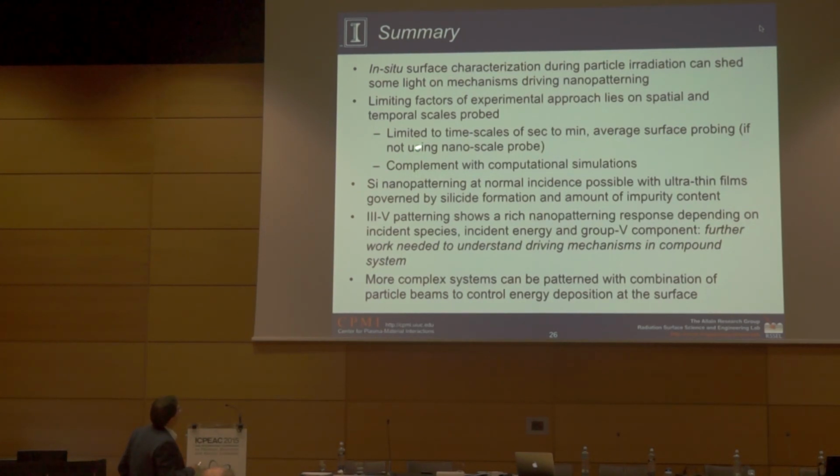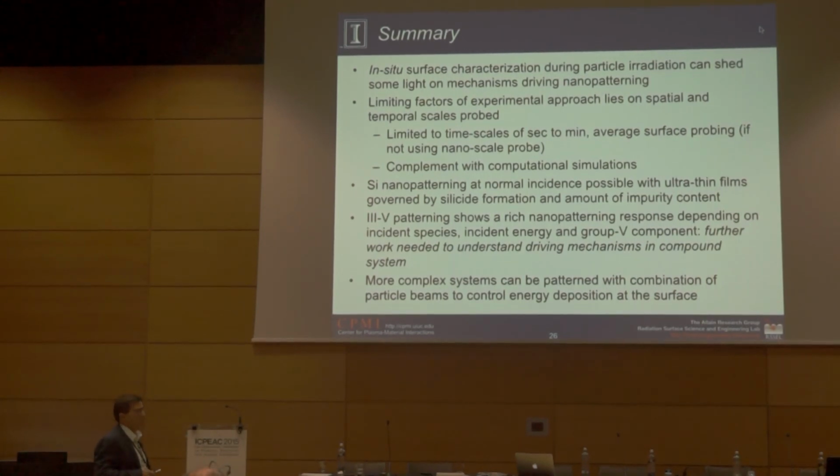So there is a very important need to complement this with computational simulations, and some of these prompt effects are now being studied by computational tools in our group. And we find that in these semiconductors, the driving mechanisms are related to compositional changes, understanding the fundamental binding mechanism, and also enhanced surface diffusion is part of the story of inducing these patterns.